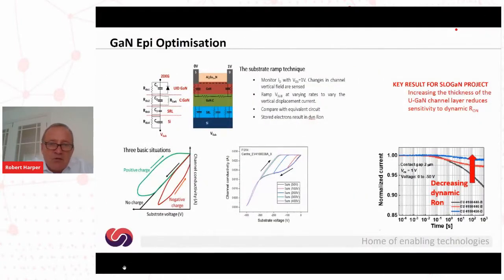So that may look a little small to you, but the cross section on the top left of the slide shows the structure of what we're doing here. So we're basically starting with an 8-inch silicon wafer. These are 1-1-1 orientation, which facilitates the growth of gallium nitride. And then we'll grow in something called an SRL, or stress relief layer. This layer allows us to adjust the lattice constant between silicon and gallium nitride by transitioning from one lattice constant to another.